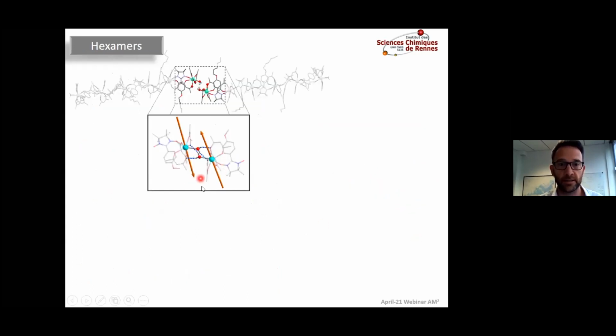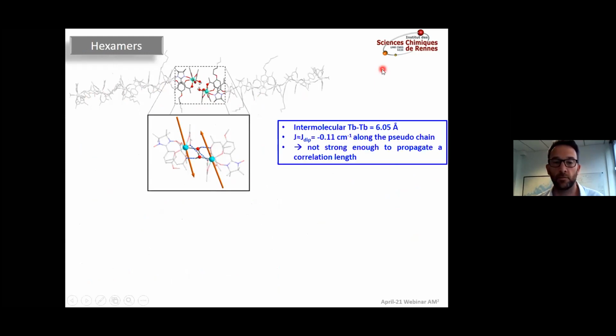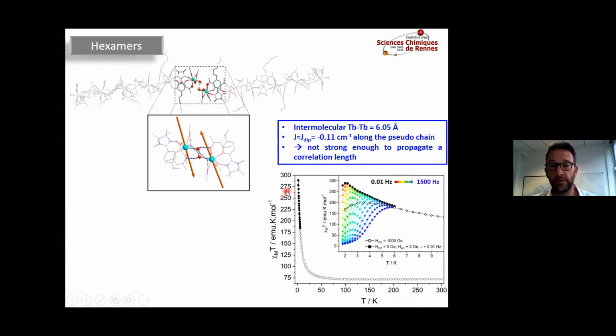So just analyze this a little bit. You can see that between 2 hexamers here, we have water molecules that are interacting, a very classical picture that we can see on beta-diketonate. And obviously, the calculation shows that with this terbium distance, dipolar interaction, so an interaction that is not strong enough to propagate a correlation length. So with this in hand, you can put it in a SQUID, and actually you see a correlation length, a strong divergence of chi-T. Once again, you can measure it with a 1000 Oersted field, and then you can measure with 0 field with AC, so as to be able to reproduce the full divergence.